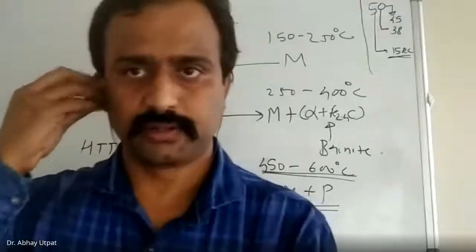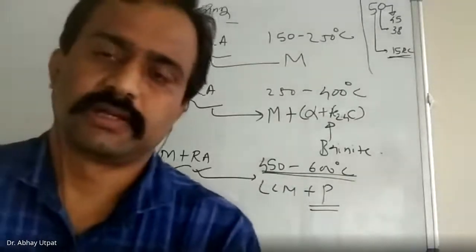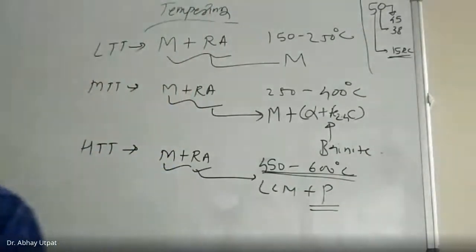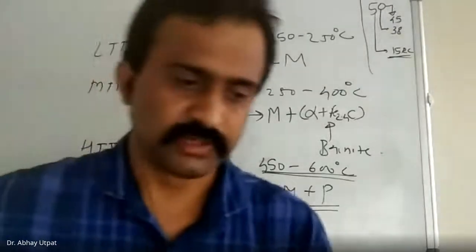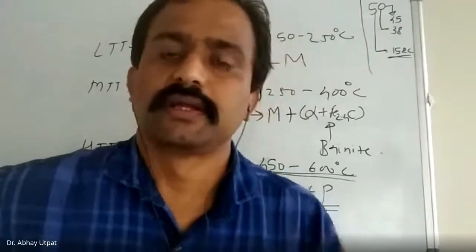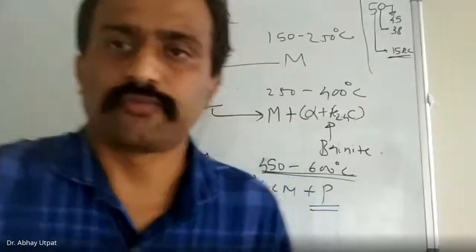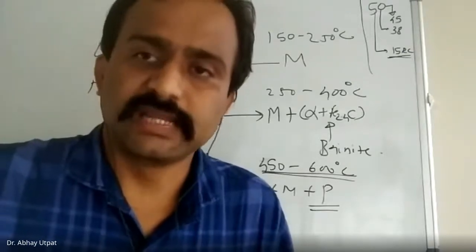are tempered in the range 450 to 600 degrees Celsius, and cooled slowly, comma, instead of increase in the toughness, comma, brittleness increases.